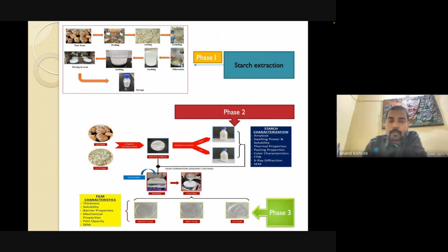HMT is a physical modification technique where the starch granules are heated at very high temperatures. Here I used 150 degrees centigrade and 120 degrees centigrade with a moisture content of 20%, and the heating time is half an hour. And again, for citric acid, we use 20% of the weight of the starch. After getting this modified starch, we go for the characterization of the starch.